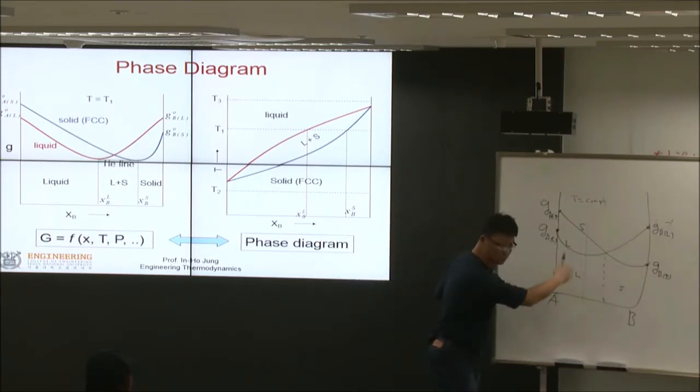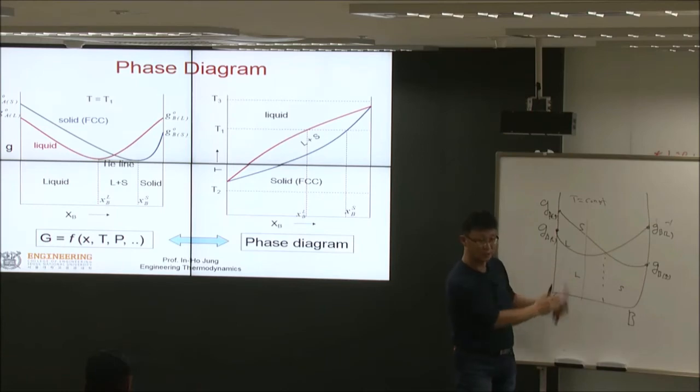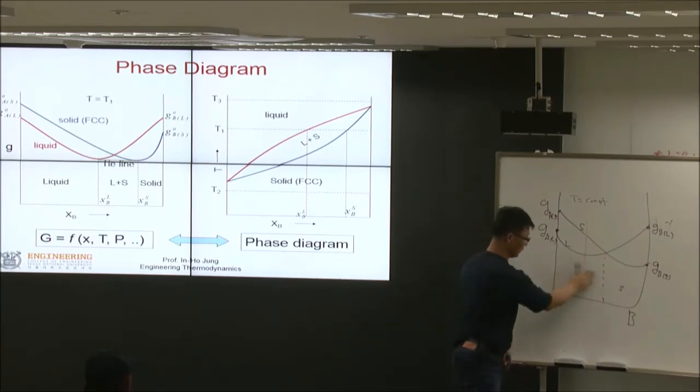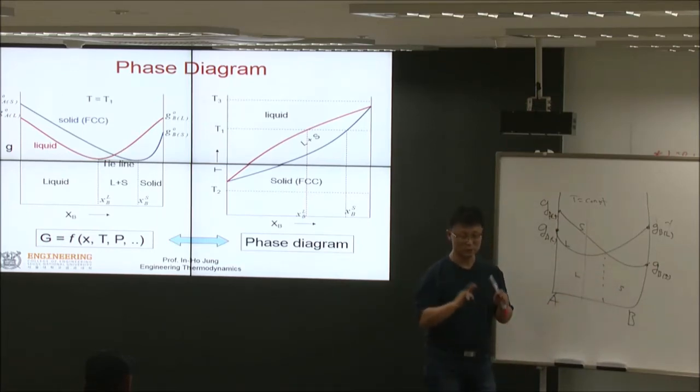The assumption I made here is that there is only a single phase: which single phase has lower energy, liquid or solid. I don't assume that two solid phases or liquid and solid can exist together. But as you see in the binary system, they can exist together. If you allow two-phase equilibrium, so that even a two-phase mixture can be the stable phase, then the story is different.